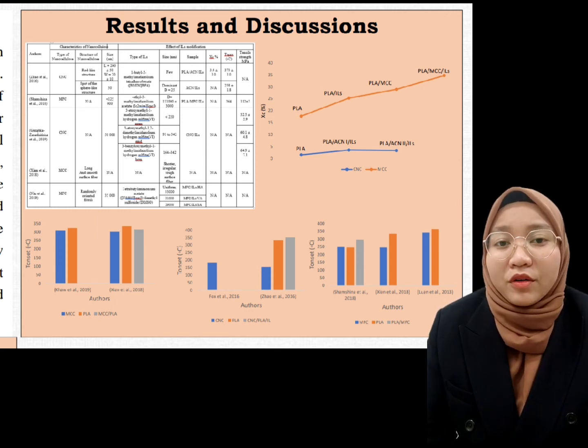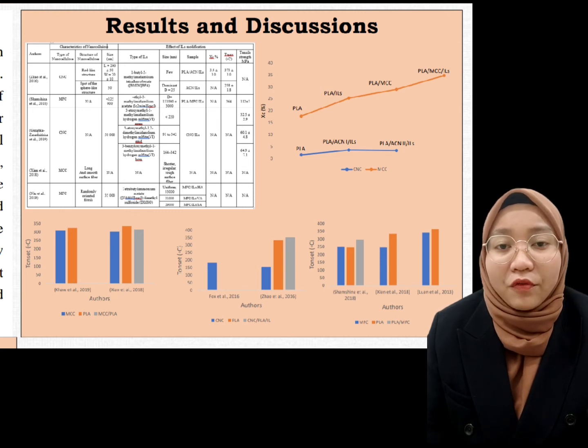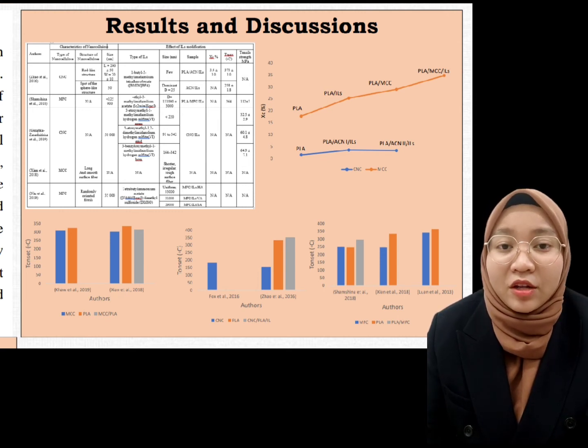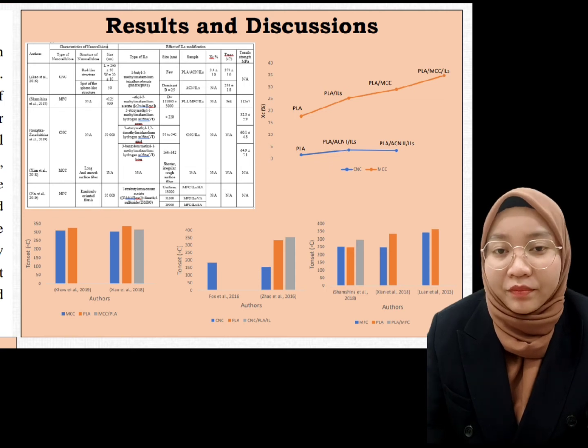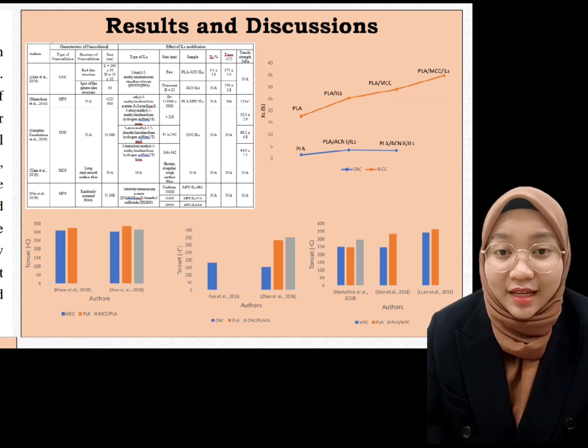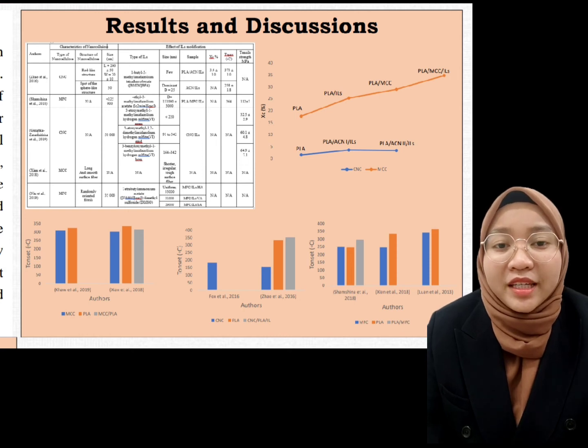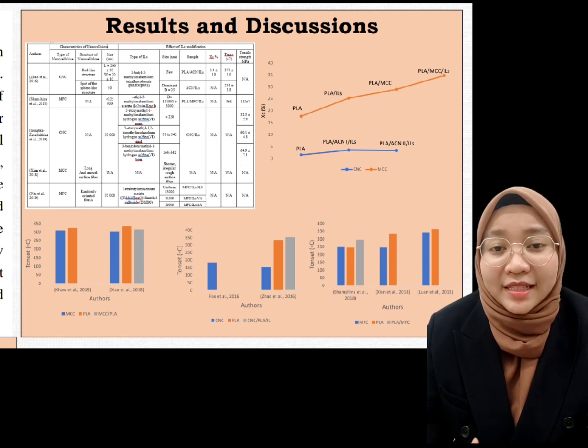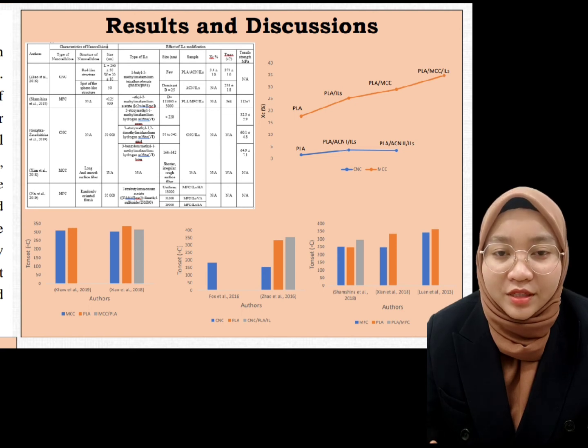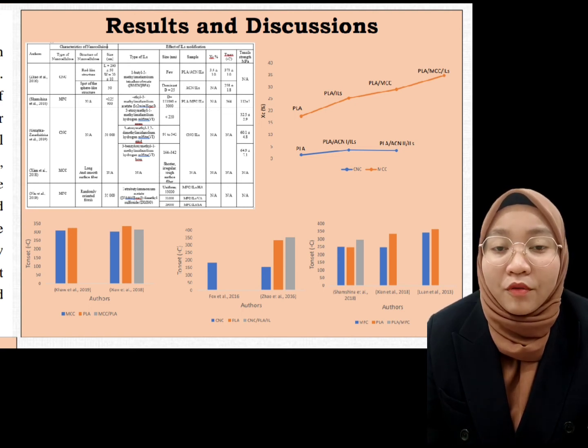The presence of micrometric particles and particles of nanometric size affected the elongation at break parameter. The smaller the distribution size is, the better. The breaking elongation of the film was much greater than the pure cellulose film. This finding suggested that homogeneous nanocellulose hybridization with the right amount of PLA might improve not only the quality of the nanocellulose but the quality of PLA too.